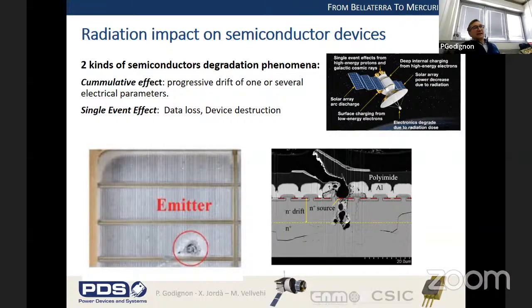So again, as I said before, semiconductors are especially sensitive to radiation, and this is important for space applications. You typically have 2 kinds of degradation generated by radiation impact on semiconductors. One is the cumulative effect, based on the cumulative dose of particles that the device will receive, which will create a progressive drift of the electrical parameters. The other phenomenon is single event effect, which is sometimes caused by only one particle, and may cause, in the best case, some data loss, for example in a memory, but usually generates directly a device destruction.